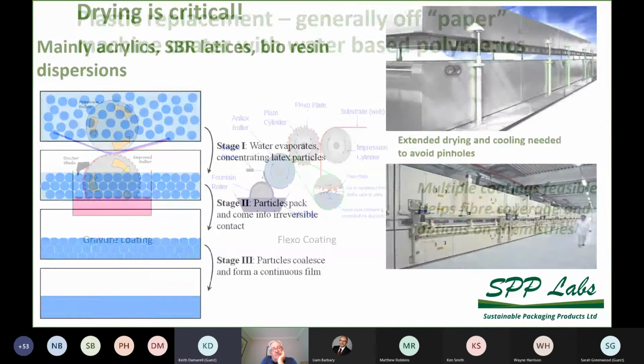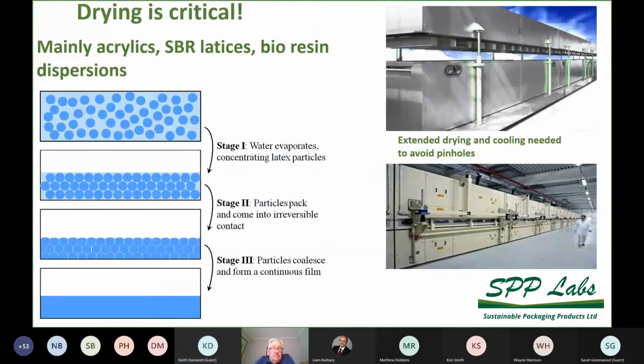We go on to the next slide, please, Liam. So most polymeric materials used in barrier coating today are based on these sort of synthetic latex materials, and they all work in a similar way. Some may be combined with some pigments like talc or clay, but they will all work in a similar way. So after coating and after they've been metered, they essentially are on the surface of the substrate as a dispersion of individual particles. Now, as the water is dried off, the particles start to pack together. And there's a key requirement in barrier coating: you've got to start the drying process gently. You must avoid boiling the water in that drying process, because if you boil the water, it causes bubbles, and those bubbles cause pinholes. And if you have a pinhole, you lose the barrier functionality.